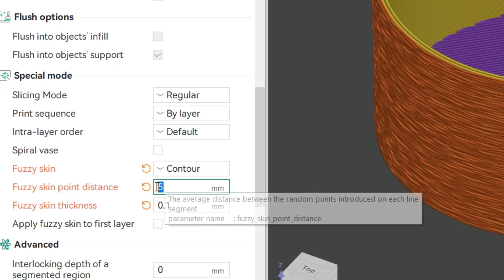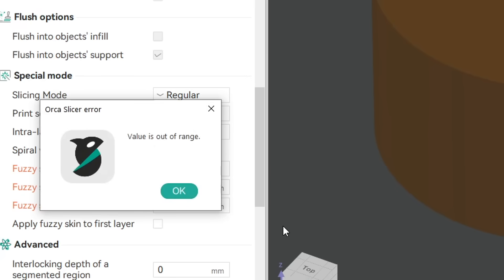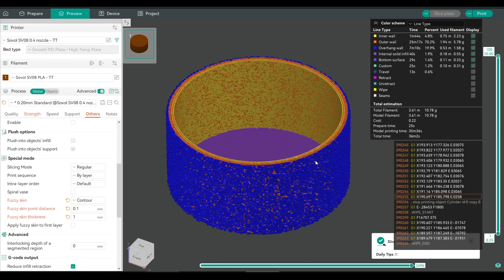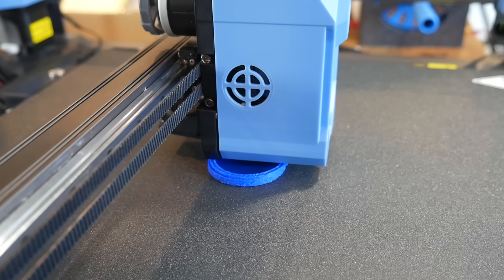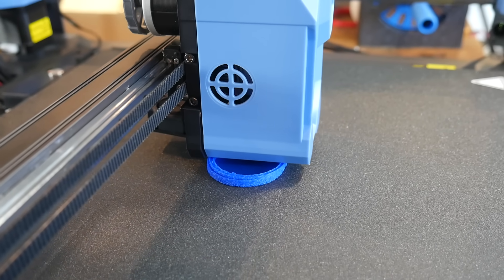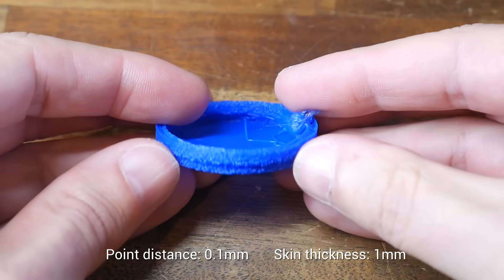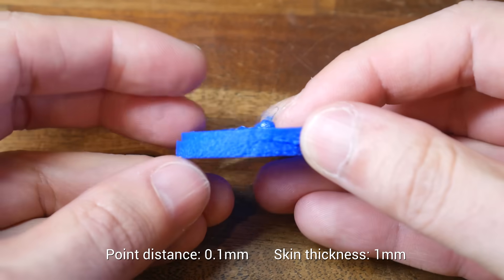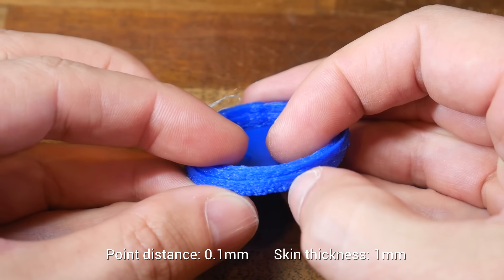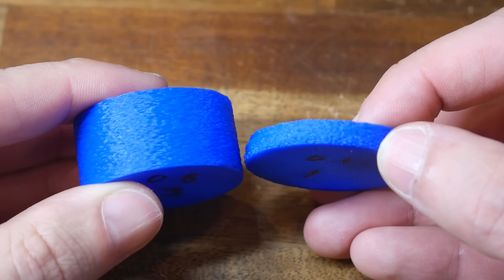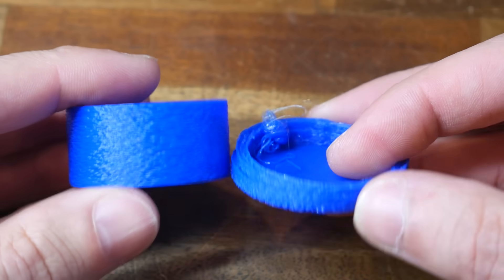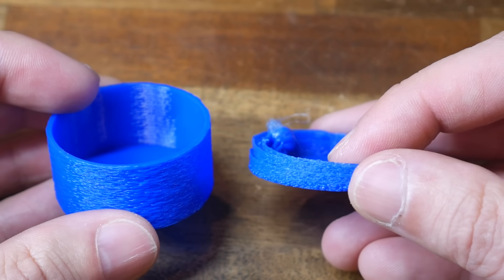So how about that in reverse? Let's do a very small point distance, but then do the maximum thickness where allowed, which comes down to 1mm. As we can see, the Fuzzy Skin is very aggressive now, to the point of coming through the two outer walls and into the interior of the shape. And if we zoom in, we can see this much clearer. This aggressive texture can be problematic when it comes to 3D printing. The overlapping of the Fuzzy Skin with the normal perimeters firstly caused a layer shift and then knocked the entire object free. But if you can get it to stick, this will give you the most aggressive texture by far, which we can see when comparing with the default values. The take-home here is that we can tweak these parameters to suit various applications.